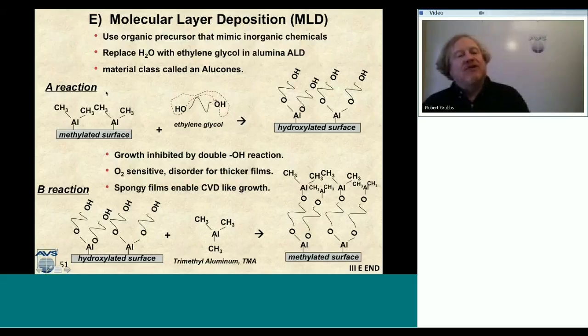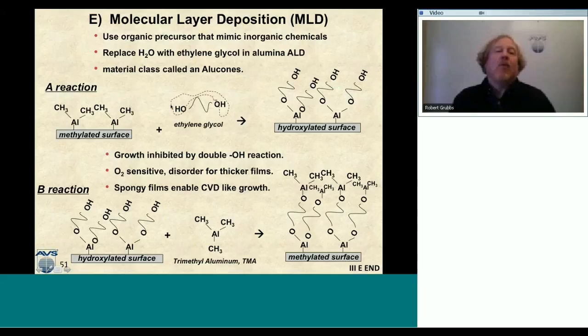So here's a methyl-terminated surface of aluminum methyl bonds. I come in with ethylene glycol. Now one of these OHs is going to react with that methyl group and make an oxygen aluminum bond, and then this organic moiety will stick onto the surface, producing an OH surface. Then in the B reaction, I react that OH surface with trimethyl aluminum, and those OHs on the surface will react with the methyl groups, again creating an oxygen aluminum bond and recreating this methyl surface. So that's the basic part of this.